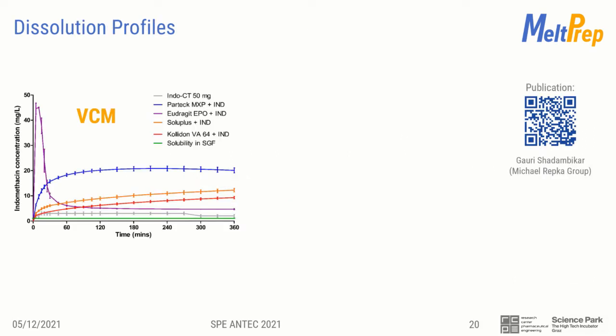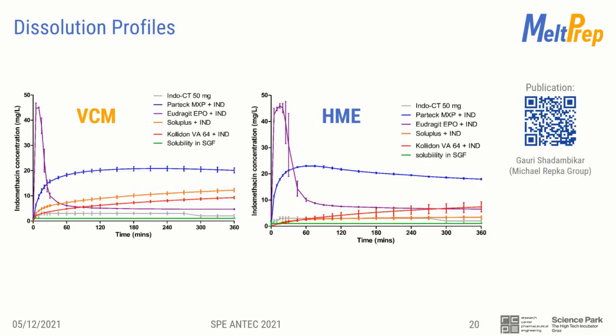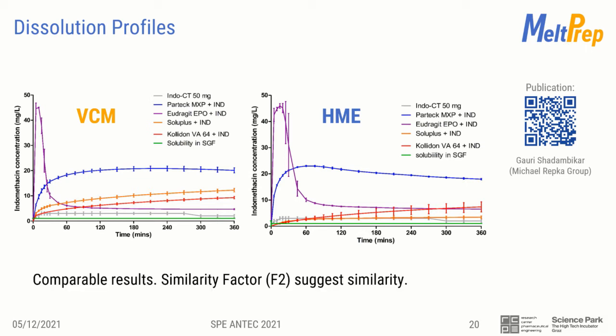I want to highlight the dissolution data. The VCM and extruded samples were both milled and then subjected to dissolution. One can see significant differences between the carriers, but you can also see an excellent agreement between VCM and HME. It proves VCM as a screening approach, giving extrusion-like properties and requiring only a small fraction, less than a gram of material per formulation. Their paper is open access and linked on the QR code on this slide if you want to read more about this.